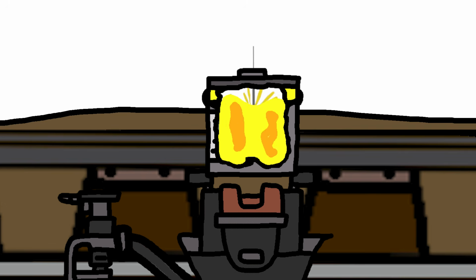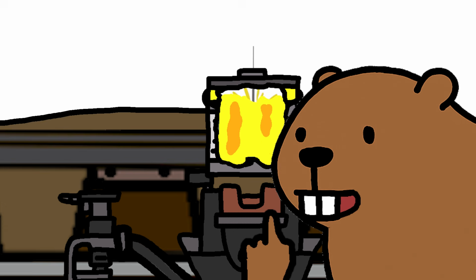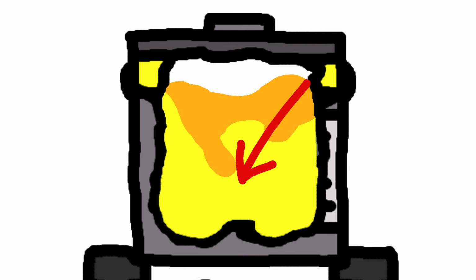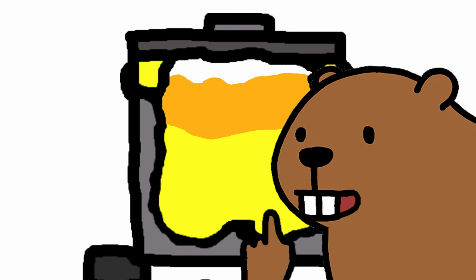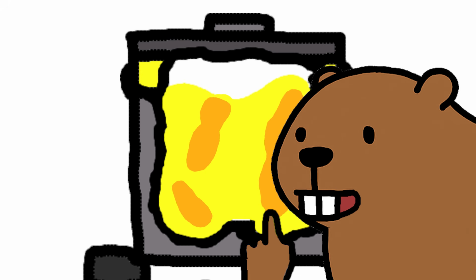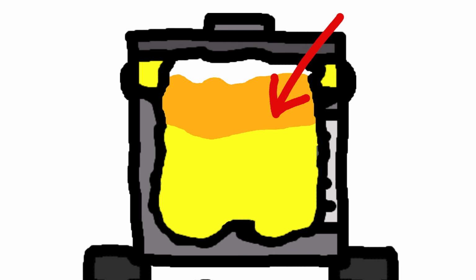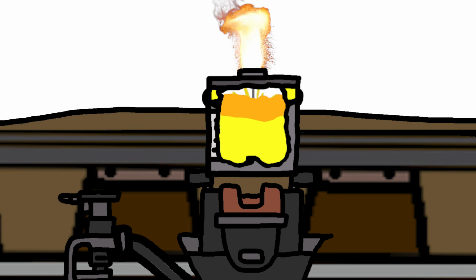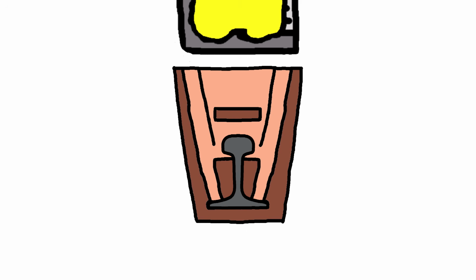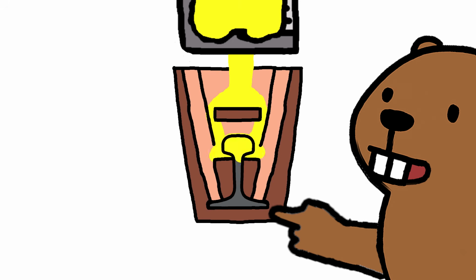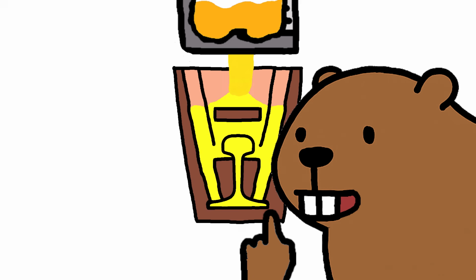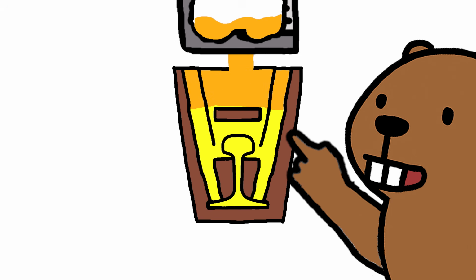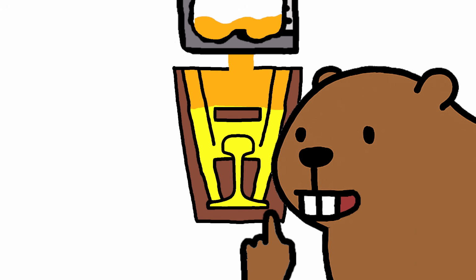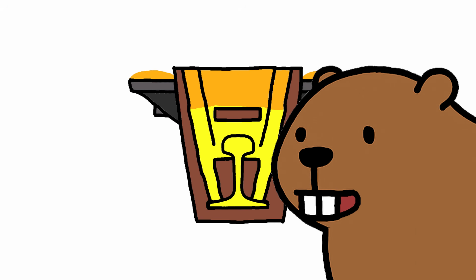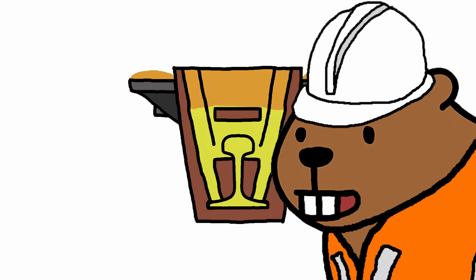As it continues, the metals will begin to separate. The liquid steel will naturally sink to the bottom due to its higher density, whereas the liquid aluminum has a lighter density, so it will begin to rise. The molten thermite will eventually melt through the crucible. When this happens, the steel will pour into the mold first and fill the bottom. Then, the aluminum will enter next and float on top of the steel, causing it to flow into the slag pens. As the molten metal begins to cool, Beaver engineers carefully monitor the cooling time.